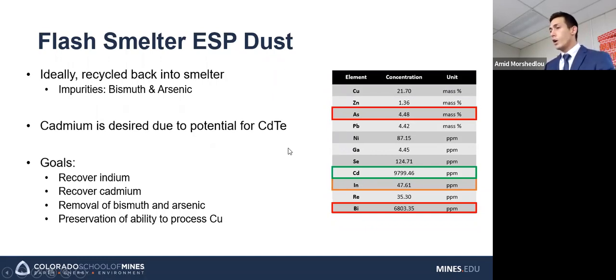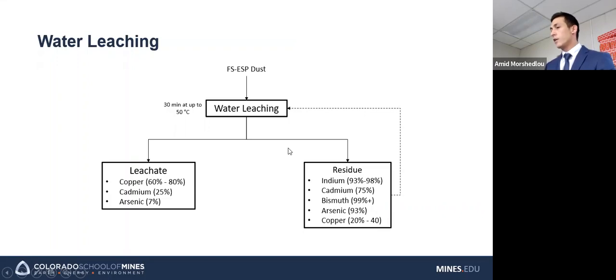So what do we do? We looked at a few things and settled on water leaching. The reason this worked is there's a pretty high sulfur content in the dust already, and also some of it was copper sulfate. So what happens when we subject the dust to water is we get some of the sulfur reacting with the water to form some sulfuric acid, not much, but enough to get the job done.